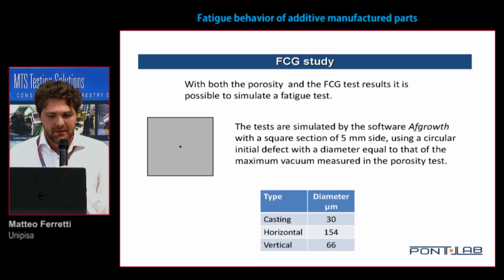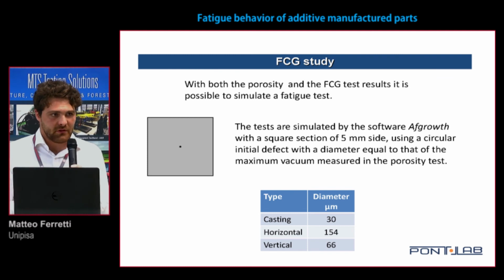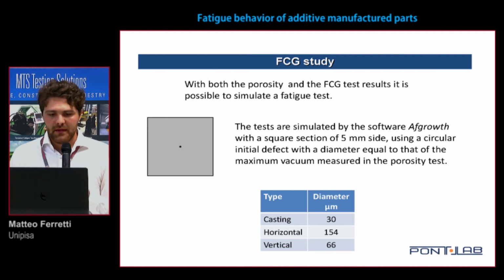With both these test results, the porosity test and the FCG test, it's possible to simulate a fatigue test to obtain the SN curve, stress and number of cycles. The tests are simulated by the software AFGROW with a square section of 5 millimeters, using a circular initial defect with a diameter equal to the maximum void measured in the porosity test. In the table, we can see the maximum dimension for each type.